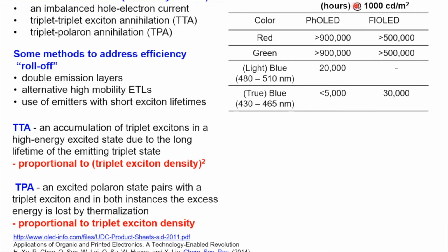If you look, for example, here at the stability, which is defined as the time it takes for the initial OLED intensity to drop to 50%, for red and green emitting OLEDs, the phosphorescent type, they've got greater than 900,000 hours, so excellent stability. And that's even better than the fluorescent OLEDs.